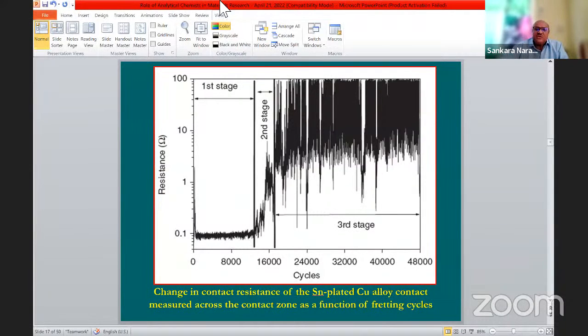Okay, what happens is, during the initial period, the resistance is very, very low, only around 0.1 ohms. Up to nearly 12,000 cycles, there won't be any problem. Beyond that, the contact resistance starts to increase. And when we go to the third stage, beyond say 17,000 or 18,000 cycles, the resistance increases to more than 10 and reaches even 100. That means it automatically becomes an open circuit. So your dashboard will not work, your particular indicator will not work. Okay, so we should not reach this stage. We should be able to prevent it at this stage.